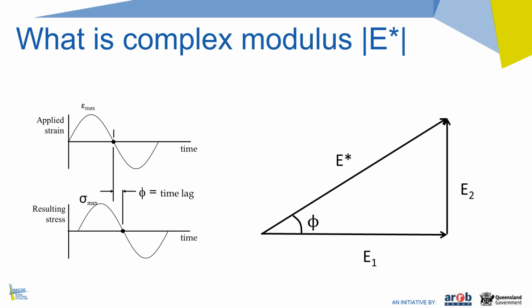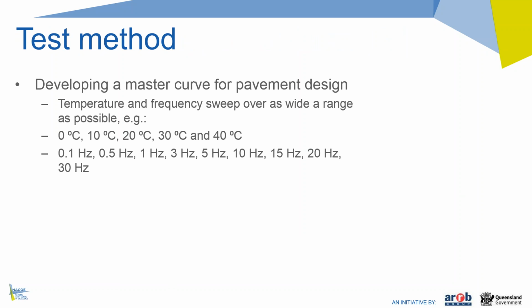The value of the complex modulus is actually not that much different for normal mixes in the normal temperature and frequency range than the flexural stiffness. However, it's not the same, and therefore we'll be using this, and that's basically the difference. Brings me to the test method.